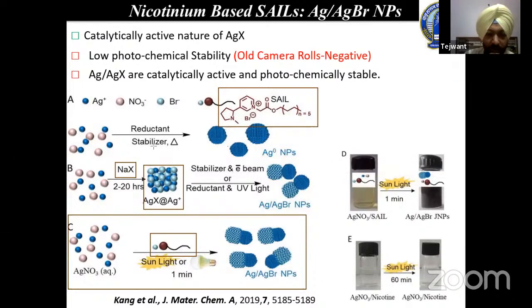Now one can ask, from where would the halide come? We have not added the sodium halide from outside. Actually, the bromide ion is utilized as the counter ion of the surface active ionic liquid. So the bromide ion was provided by the surface active ionic liquid for the preparation of nanomaterials. Here, one surface active ionic liquid acted as the source of bromide ion, aids in the reduction, as well as acted as the template.